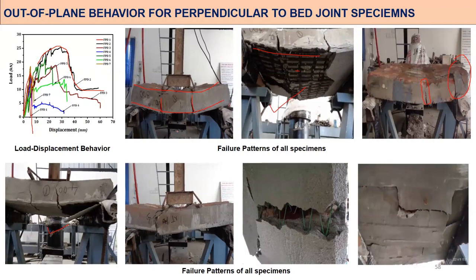So we have used polypropylene. This is a polyester based geogrid, and this is a polypropylene based geogrid, which is almost like a plastic. You can see how it bridges the crack, and how it is yielding. And this is FRP, with delamination and rupture. So when you use various types of textiles, the failure pattern changes accordingly and the capacity changes, and the strength of the grid matters.